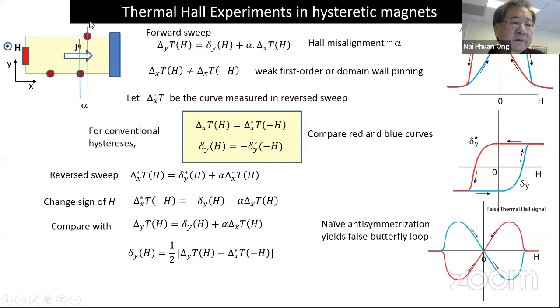So remember, when you make a thermal Hall measurement, you pray that the thermal Hall contacts are aligned, right? That they are perfectly aligned in the transverse direction perpendicular to the heat flow. But of course, that is impossible to achieve. And if you have a very large variation in the longitudinal gradient, you will always pick it up. So alpha is the measure of misalignment. Alpha could be as small as 1%, which is already quite good, right? But if the longitudinal signal variation is 1,000 times larger than the Hall signal, then this will come true and dominate the Hall signal.